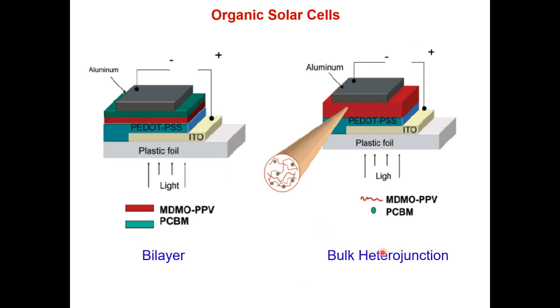The last problem I told you is that you don't want to play with a bilayer because you are going to lose many excitations. They will not be converted. And so the trick is to make a very intimate mixing of the two materials, the polymer and the acceptor. And you want to make what we call a bulk heterojunction, to have a nanostructuration so that you're sure that when you make an excitation, there is always an interface nearby.